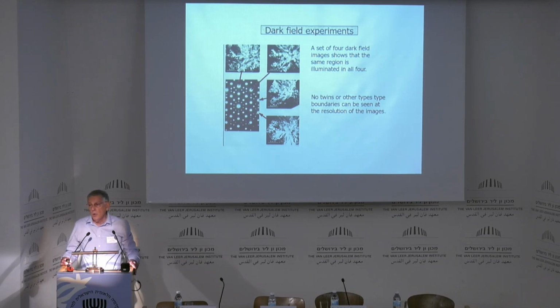Now, I said, okay, maybe they are very, very small, and this was not a high-resolution microscope. It was a Philips 400, by the way, for those who are interested. Let's make a microdiffraction. In microdiffraction in the electron microscope, you focus your beam onto the smallest spot that you can, and on that microscope it's called 400 angstrom, 40 nanometers. This was the diameter of the spot. I could not get any smaller than that.